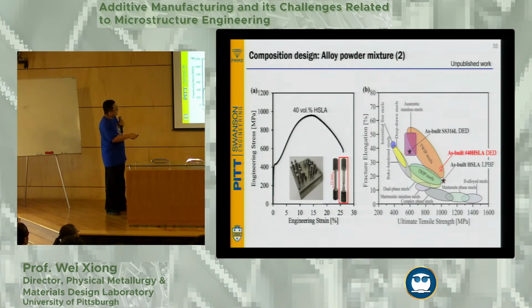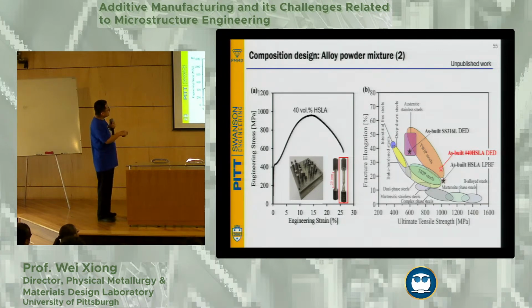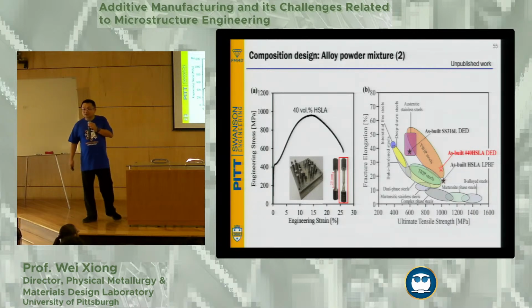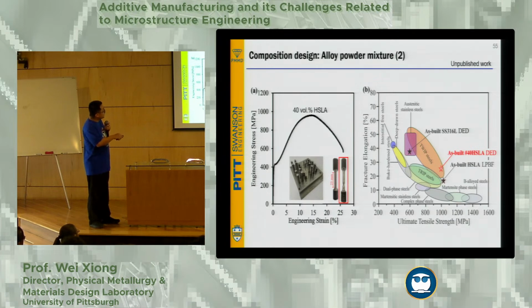So we print 40%. This is a single composition, a totally new alloy composition at 40%. We do the tensile test, and as you can see, the elongation is actually quite good, and the UTS and yield strength are also good. If you put this into the Ashby plot, this is the fracture elongation and this is UTS, and you can see this is the parent alloy, 316.